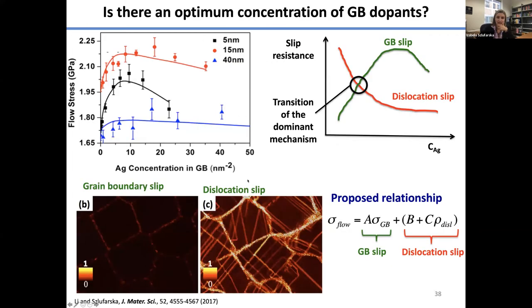So let me just show you the last slide here, where we also asked, if we're looking at dopants, whether there's an optimum concentration of the grain boundary dopants that is going to make the material stronger. And the answer is that for nanocrystalline material, yes. This is based on our molecular dynamics simulations, in this case of copper doped with silver. I alluded to those earlier. You can see the strength of the nanocrystalline copper as a function of silver concentration, and the different colors, different grain sizes, have a maximum for a certain dopant concentration. So there's an optimum concentration that you want to have.